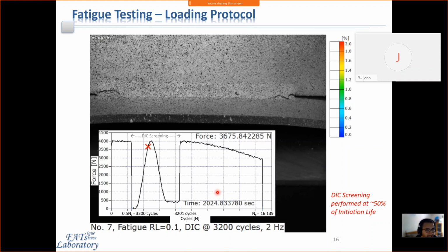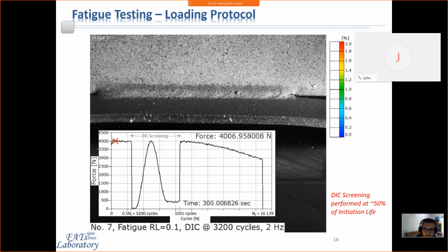Like I said, in the maybe 10 millimeter crack length, it might turn into the member, and then the member will eventually fail. So that's a possibility too. But the initiation is always in the weld thus far, which kind of makes sense just because the highest stress concentration is right at the tip here at the edge. Okay, we'll go to the next slide.